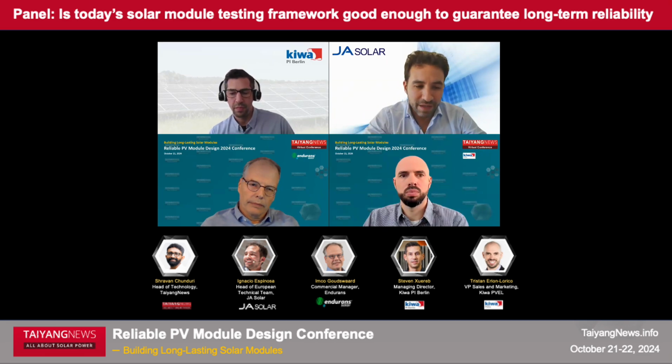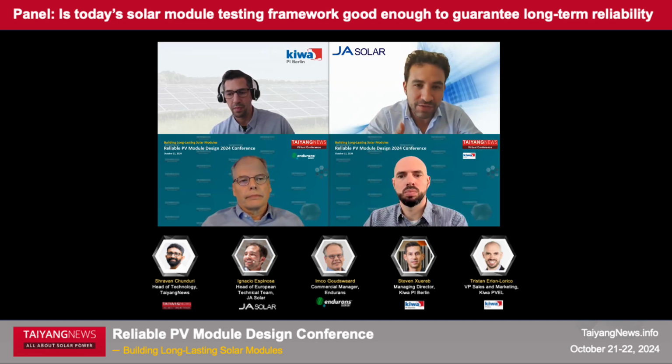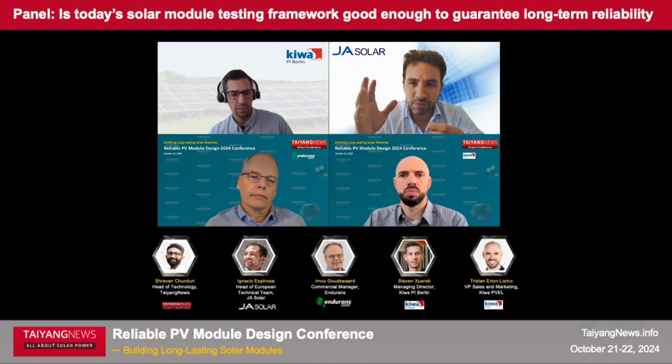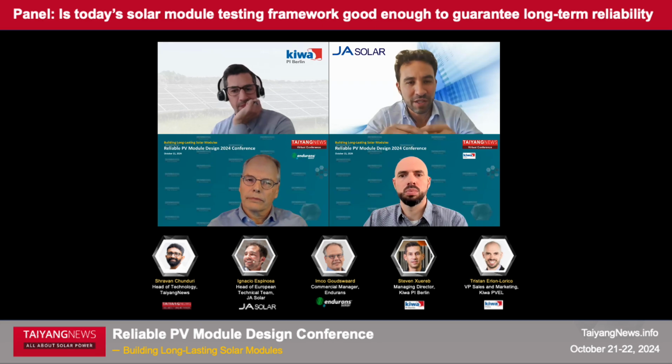results. In our case, when we realized that, reliability for us is going first. So we were probably not reaching the same efficiency that we could reach by not sacrificing those values. And as I mentioned during my presentation, we were detecting higher values than the ones we were detecting in PERC, in a range of 2% or even 2.5%, even reaching 3% in some samples. Then we started to use different combinations of the BOM to reduce it.